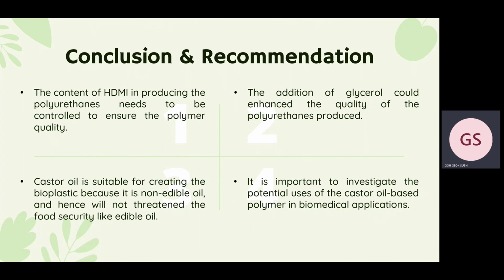Furthermore, the quality of the PU polymer produced can also be improved through the glycerol addition in the synthesis process. It is found that the application of the glycerol will lead to the formation of the cross-linked hard and soft domains within the PU polymers and also cause a promotion of the hydrogen bonding. As a result, the hard polymeric domains that form will be more than the soft polymeric domains. As the cross-linking density of the PU polymer is increased, the tensile properties, hardness, and the chemical attack resistance of the PU polymers created can be enhanced as well. Additionally, the hard polymeric domain formed will also promote the biocompatibility of the castor oil-based PU polymer.